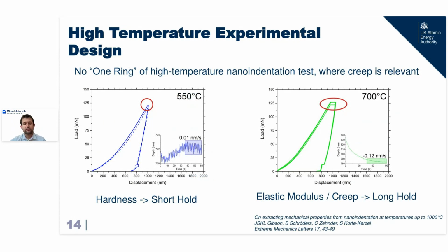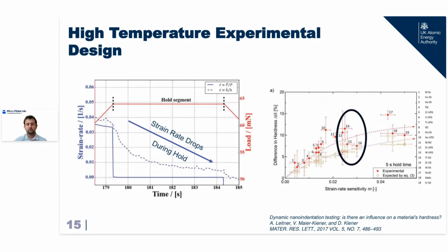The reason why you don't want a long hold for the hardness is demonstrated best by work out of Leoben. This is comparing continuous stiffness measurement with load hold tests, but the principle remains the same. Essentially, once you start doing that load hold segment, your strain rate starts dropping. And because your hardness is dependent on strain rate, what you measure will be a strain rate at the end of the test, but what you think you've done is a strain rate at the start of the test. And you don't need a very strain rate sensitive material.